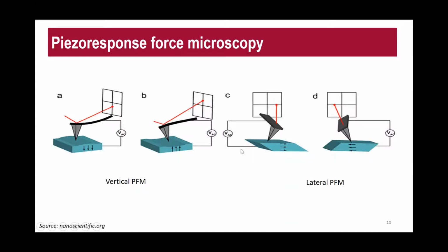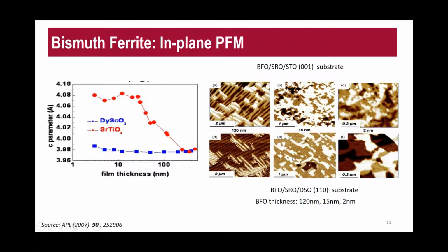So maybe we can have a look at one of the examples. These are in plane PFM images measured on a BFO film of varying thickness, ranging from 120 nanometer to 2 nanometer. The three different tones, as you can see from the images, consist of white, black, and brown. A very dark brown we name as black. These correspond to 4 variants, because bismuth ferrite has 4 variants of polarization directions. This measurement allows us to see the different contrasts, and these typically indicate the orientation of the domain.